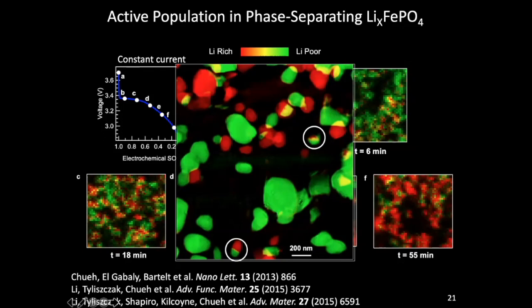So the consequence is significant. This select removal and insertion of lithium in just a few particles means that very few particles, a small fraction of the electrode, is accommodating the current. So we find that the C rate locally and globally can differ by about 50 times. So if you are charging, discharging at 1 C, locally you can be charging, discharging at 50 C. So this is a very important consideration when you consider the stability of the material.